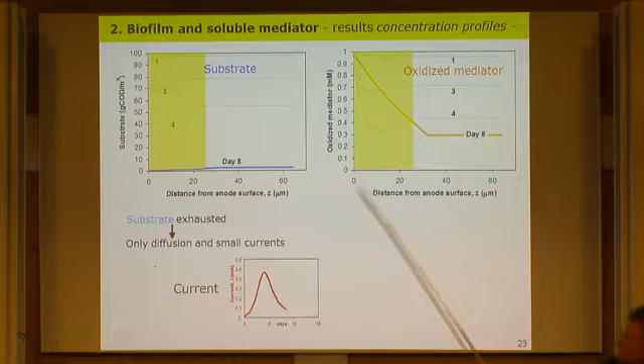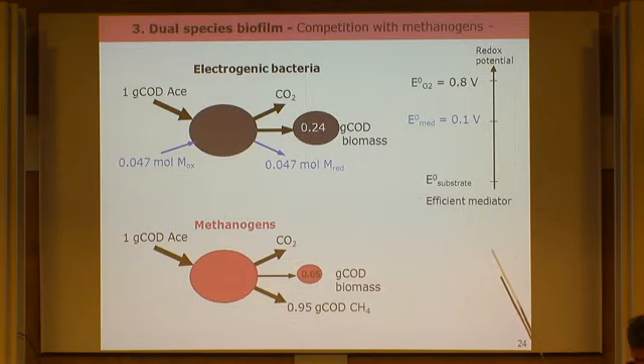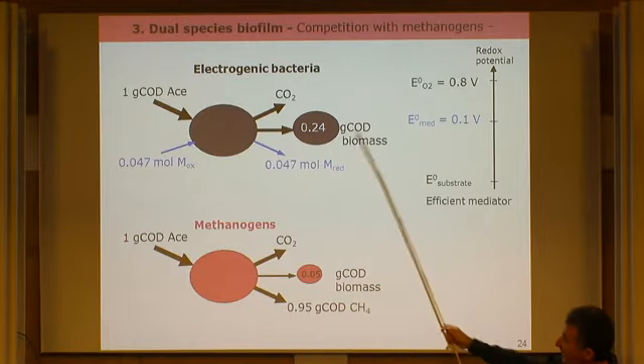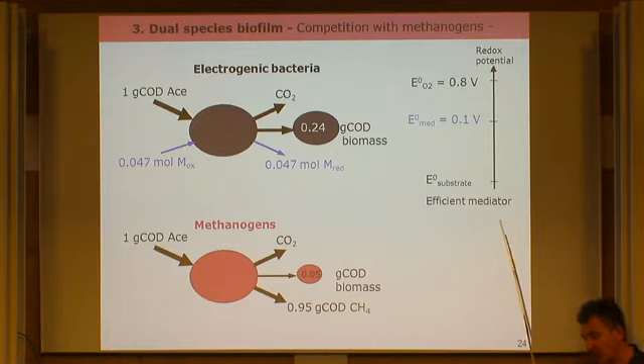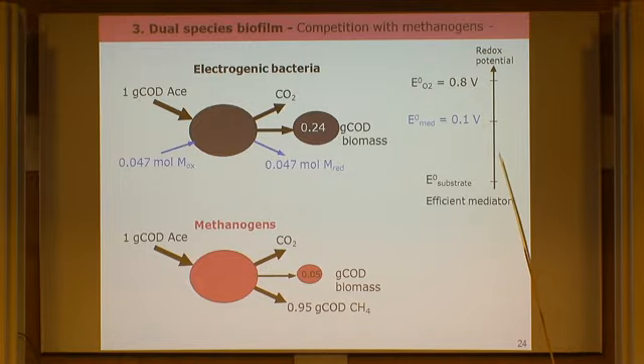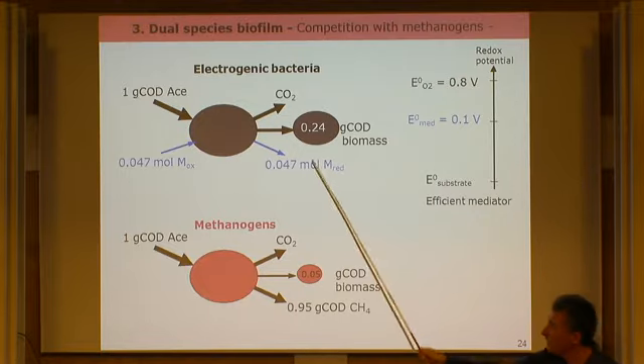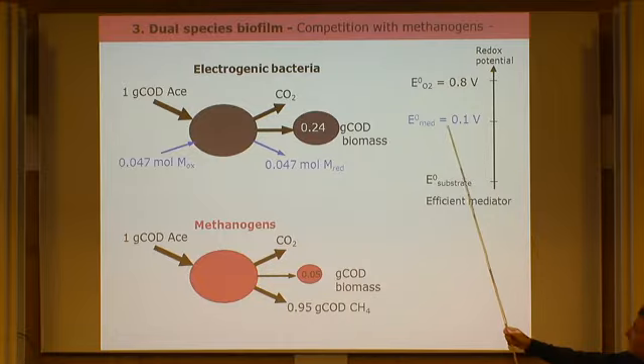And in the end, when the substrate is exhausted after 8 days of batch experiment, the current drops this way. We studied also dual systems now, the competition with methanogens. So you have these electrogenic bacteria. We can calculate some approximate stoichiometry from thermodynamics, some yields practically, given a certain standard redox potential for this mediator. You can translate everything into delta Gs, and then you can estimate the yields a bit in this case.